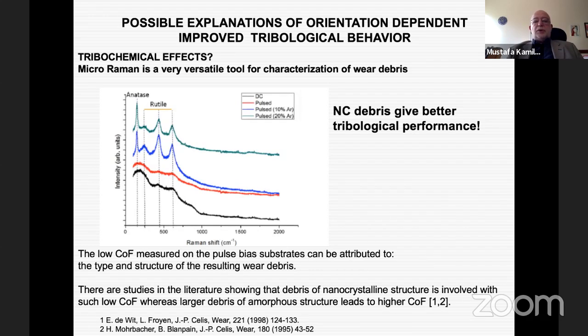So what we did then was a post-characterization of the samples that had been tested tribologically, and we looked at the wear debris. As you all know, people who are involved in tribology know that the character of the wear debris plays a very dominant role in the wear behavior of materials. So what we see is that the 1-1-1 oriented layers exhibited a nanocrystalline amorphous structure that has been very clearly observed from Raman spectra. The coatings that have been produced under pulse bias, on the other hand, show a nanocrystalline structure that is composed of a mixture of anatase and rutile. So this seems to be the main reason for this observation.